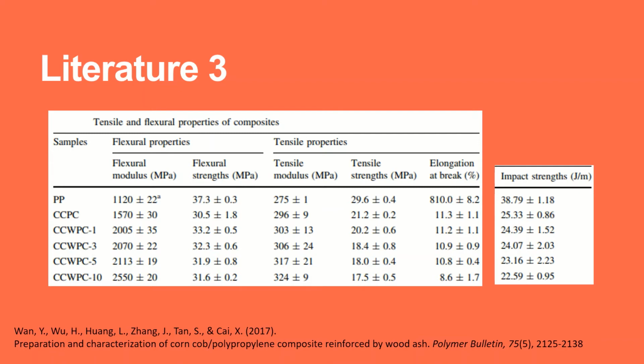Lastly, the notched izod impact strengths of the composites indicated that the addition of corn cob flour and the content of wood ash exhibited a negative correlation with the impact strengths of the composites. This was to be expected, because the addition of wood ash would disturb the continuity of polypropylene and act as a point of stress concentration, which would initiate microcracks.